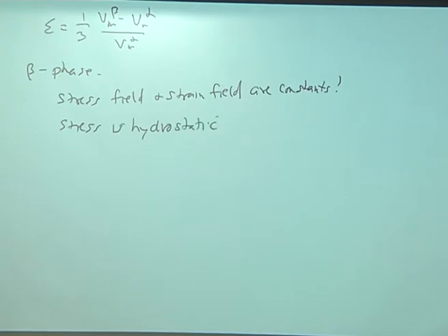So it's just like it's under pressure in the particle here. That's one important thing. And if we want to talk about the generalities, you can generalize this problem to ellipsoids. And the amazing thing about ellipsoids is the stress inside an ellipsoid is still a constant. It's always hydrostatic.